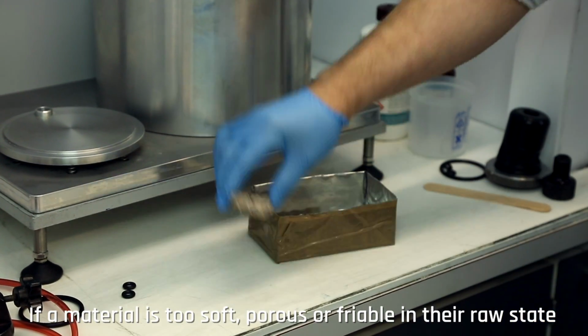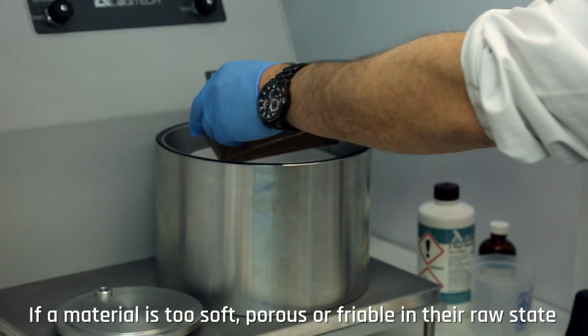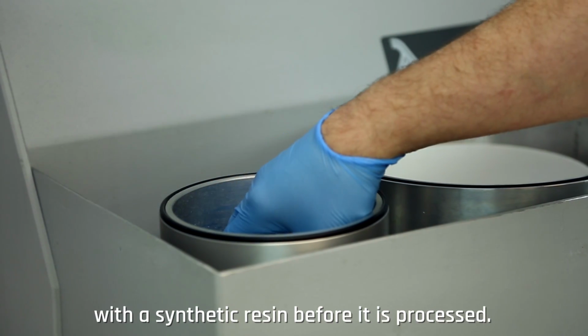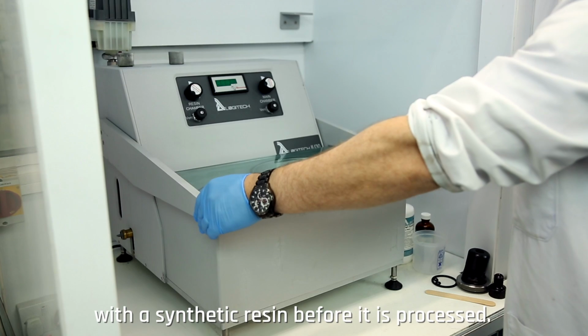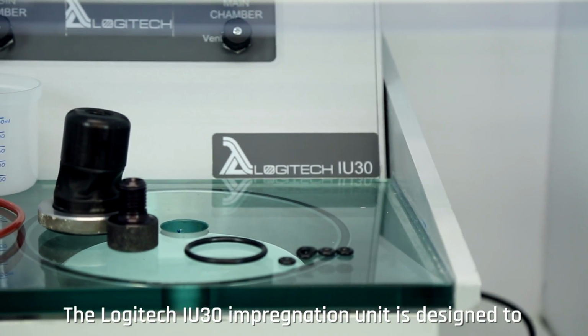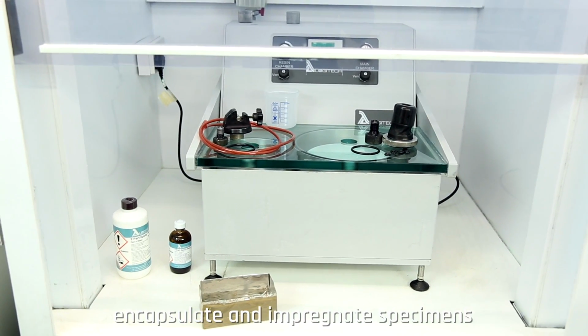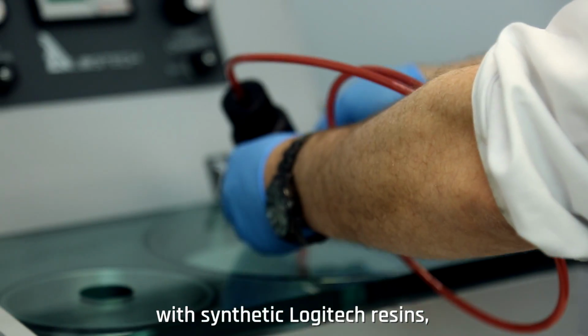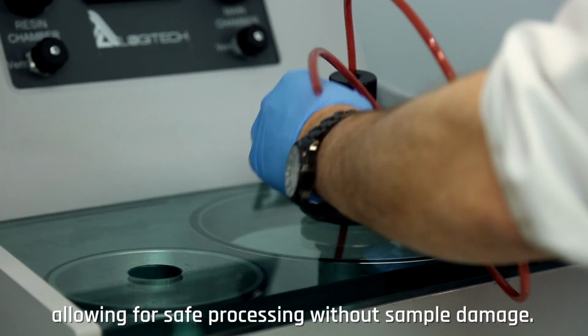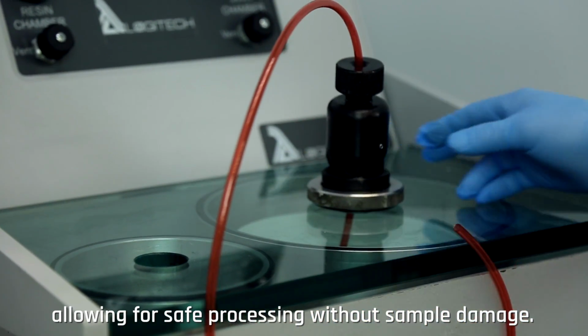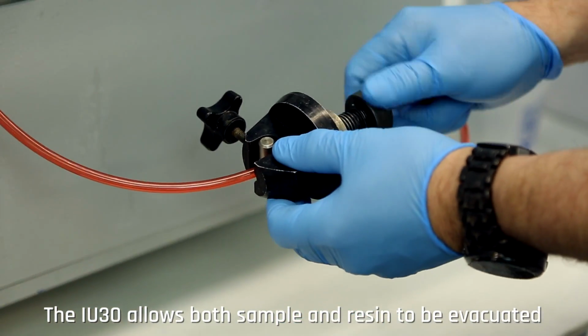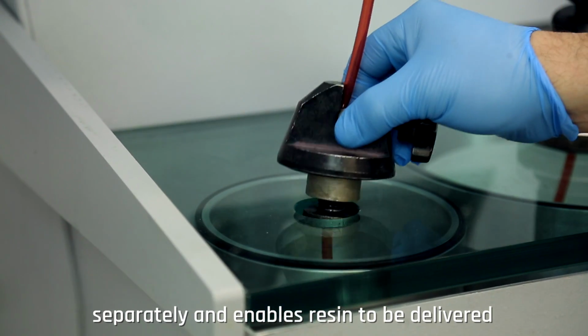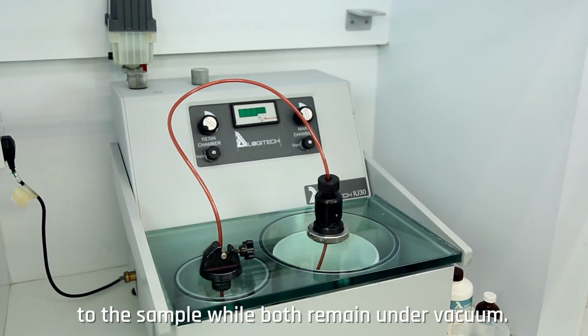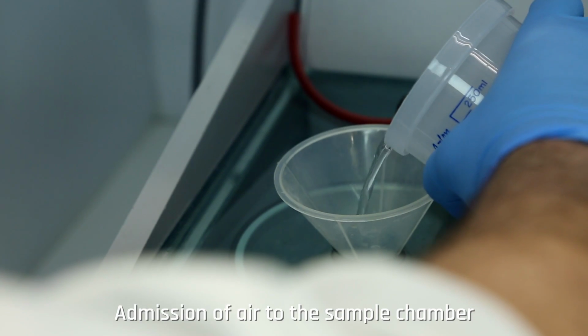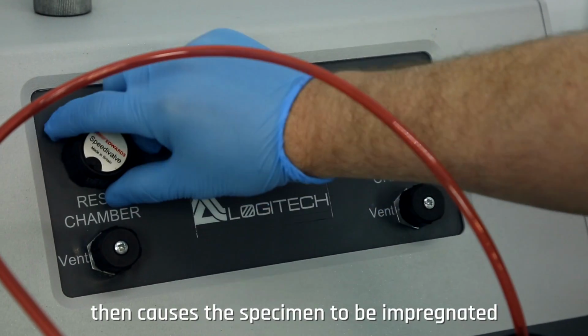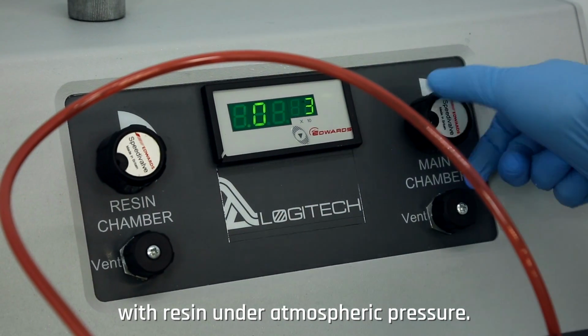If a material is too soft, porous or friable in its raw state, the material must be impregnated with a synthetic resin before it is processed. The Logitech IU30 impregnation unit is designed to encapsulate and impregnate specimens with synthetic Logitech resins, allowing for safe processing without sample damage. The IU30 allows both sample and resin to be evacuated separately and enables resin to be delivered to the sample while both remain under vacuum. Admission of air to the sample chamber then causes the specimen to be impregnated with resin under atmospheric pressure.